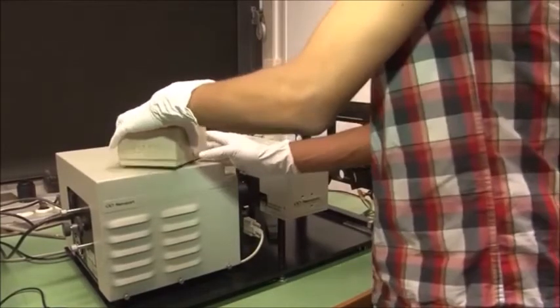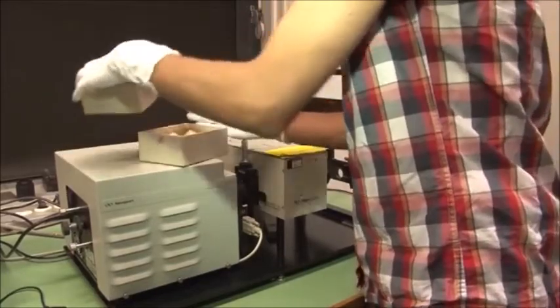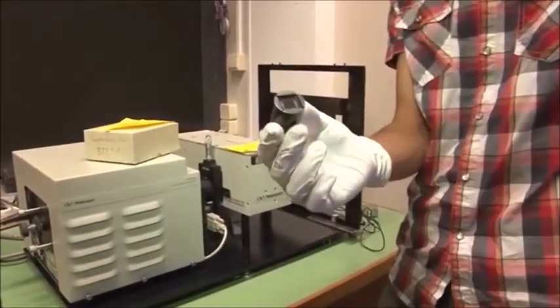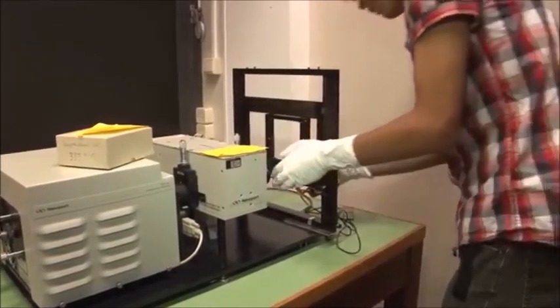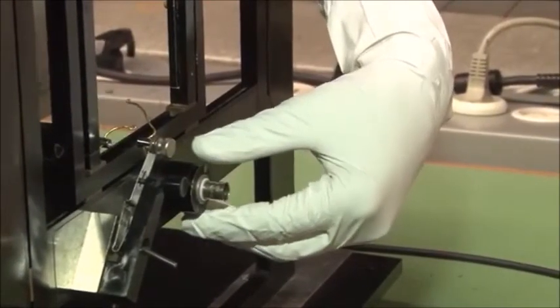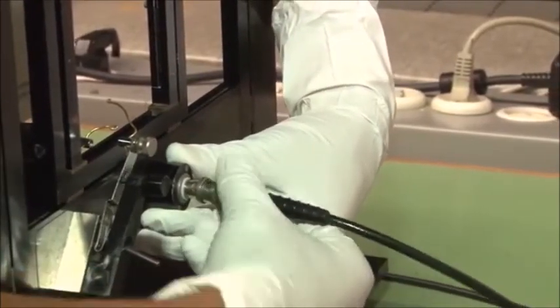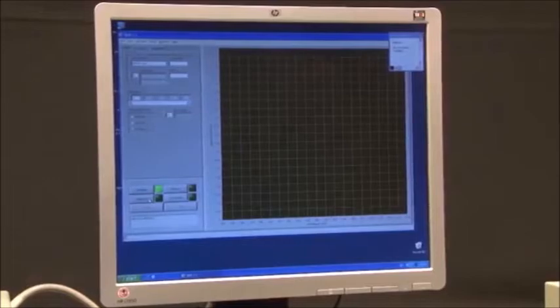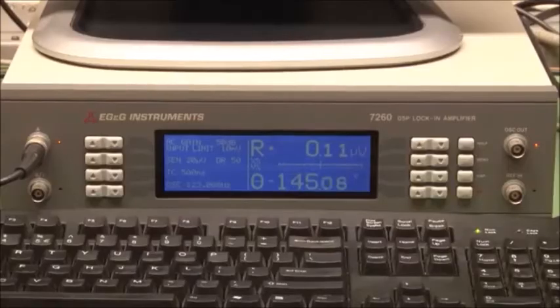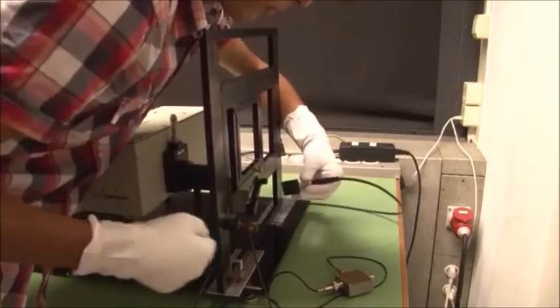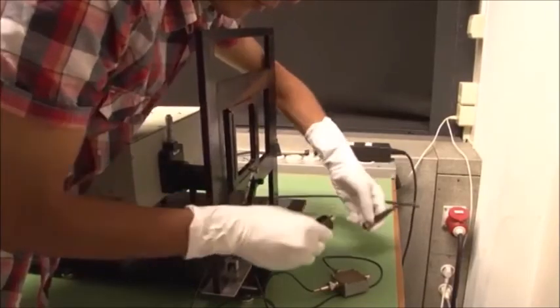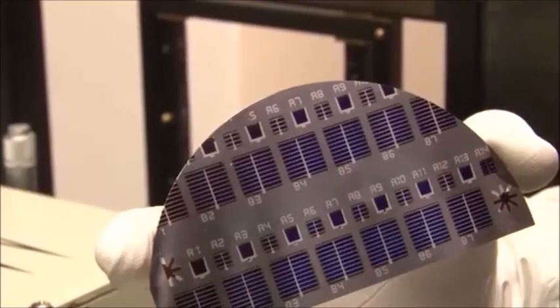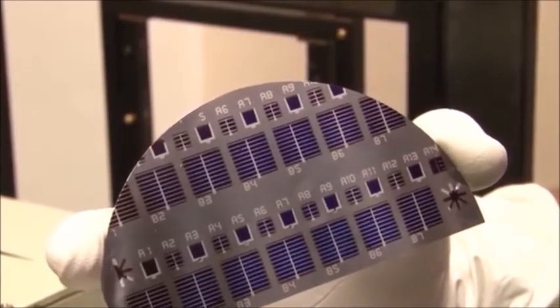We are going to measure a solar cell. This means we first have to calibrate our light source. For that, we use a calibrated silicon photodiode. This means that we can translate very accurately the light-induced currents in the photodiode to the number of photons. The photodiode signal is measured as a function of the wavelength. After calibration of the spectral power density function of a light source, we repeat the same measurement with a solar cell. As example, we use a crystalline silicon wafer-based lab-scale heterojunction solar cell, which will be discussed next week.